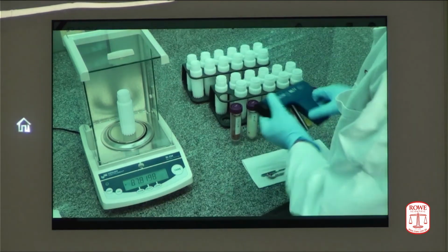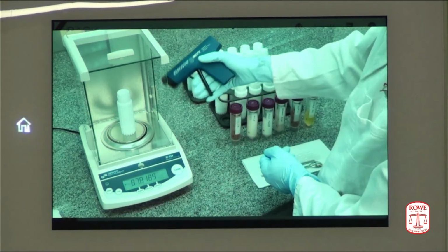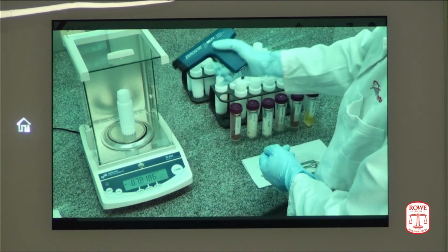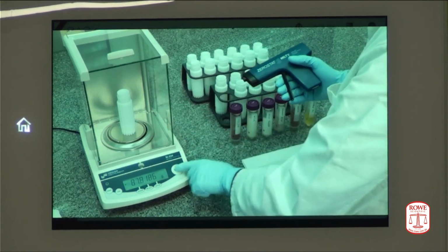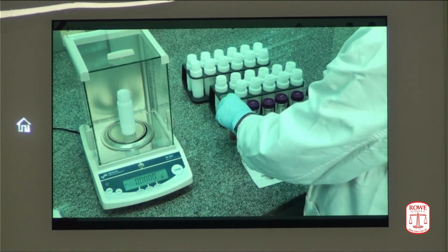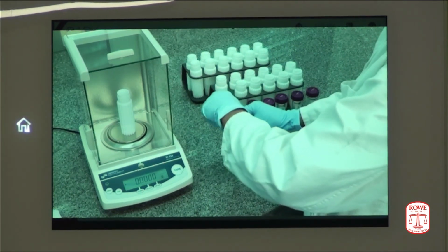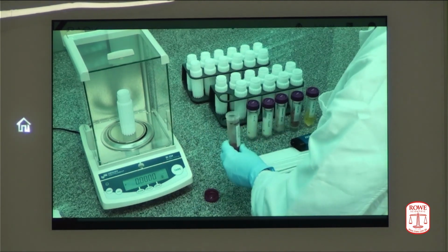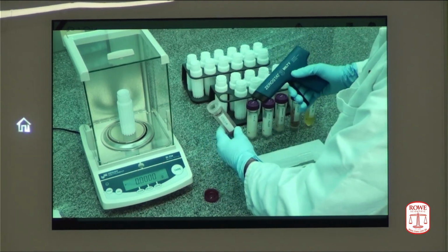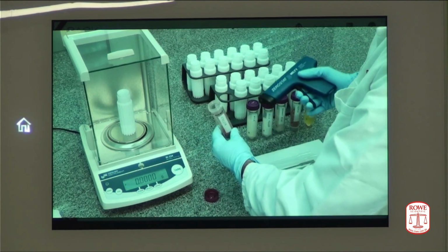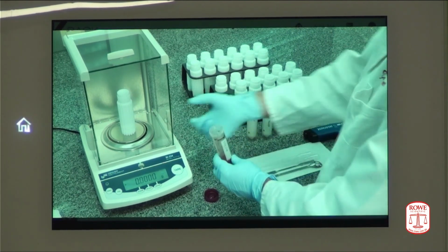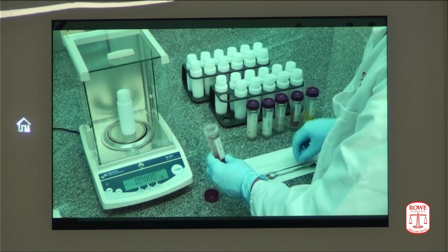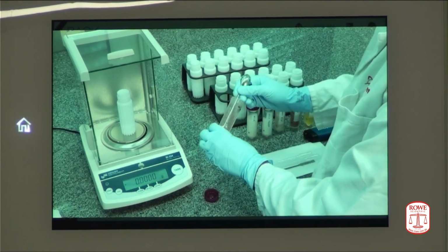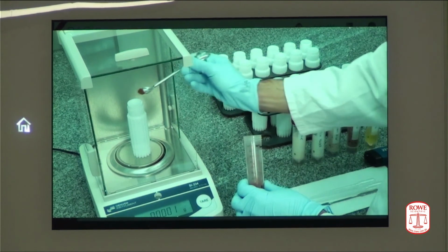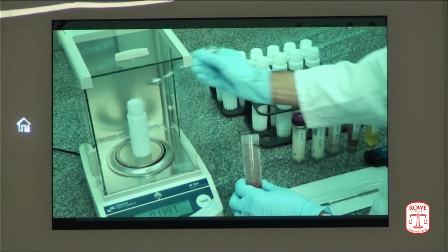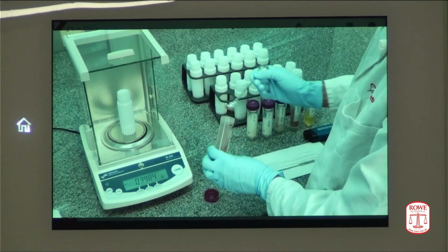So weighing of samples directly at the balance. What you see here is an anti-static gun, which is very useful in order not to have samples caught to the vessel walls by static discharge. It's a very common tool. You also do the anti-static action to the sample, first to the vial, then to the sample, and then you can very nicely fill in even powdered samples into the reaction vial, which otherwise would be attracted by the vessel walls when you pour them in.